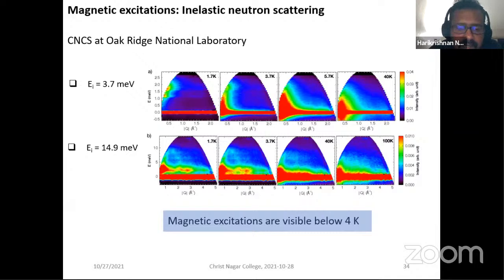Blue is low intensity and red is high intensity. You will see some red intensity building up at energy around 1 to 2 meV on the left-hand side at 1.7 Kelvin. These are the excitations that we are talking about. These excitations actually form below 4 Kelvin. And when we look at very high energy neutrons, you can see that the excitation becomes broader and broader, and starts to spread. That is in the panel below, panel B on the left-hand side.